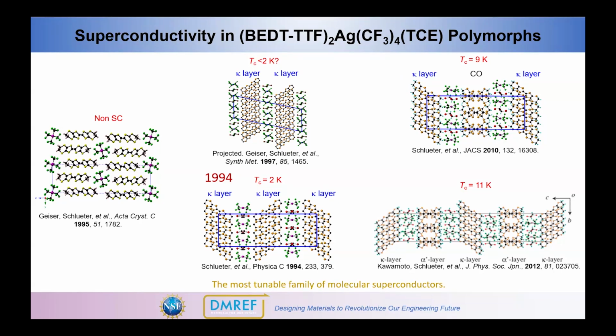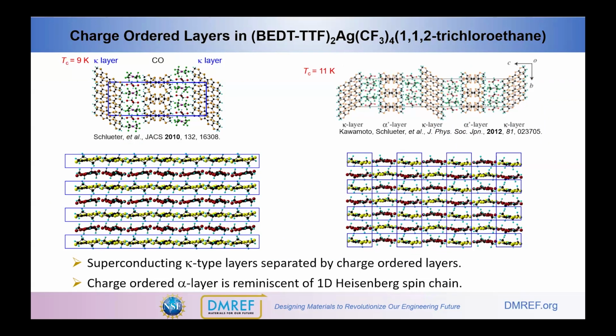The difference is whether the ET molecules from layer to layer are all in the same direction or go up and down, canting up and down with respect to each other. And then maybe more interesting is that the higher TC phase out of this group has kappa-type layers, but they're separated by charge-ordered layers. Based on the orientation of the ET molecules in the various layers, kappa alpha, the TC can either be 9 Kelvin or up to 11 Kelvin. If one takes a quick look at the alpha type layers in these, you can see that the 9K phase has the charge ordering in kind of a stripe type motif, where you have spins on every ET molecule along the chain. This is reminiscent of a 1D Heisenberg chain that would be in the insulating layer between the presumably superconducting layers in the ET salts. Whereas the 11K has a checkerboard type pattern of charge ordering